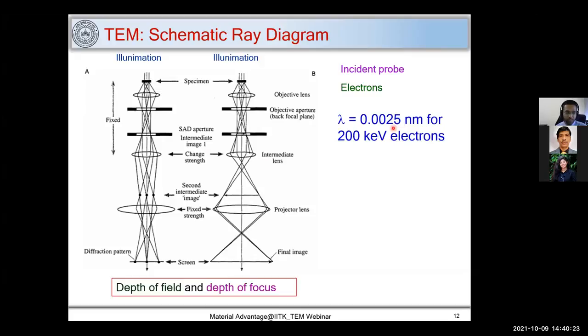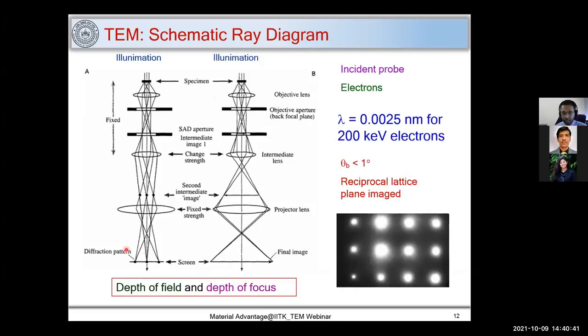And how does it help? It helps in the depth of field and depth of focus. That means my sample can be more or less focused. Depth of field and depth of focus help us keep the sample focused in TEM because of this smaller wavelength. And we can get a diffraction pattern. One diffraction pattern I have shown here is also called a reciprocal lattice or Fourier space. You can see that these rays are diffracting or diverting, but this angle is less than 1 degree. Here it is an exaggerated image, but these angles are much smaller. Most of the time they are less than 1 degree.